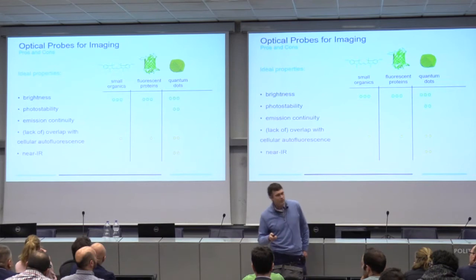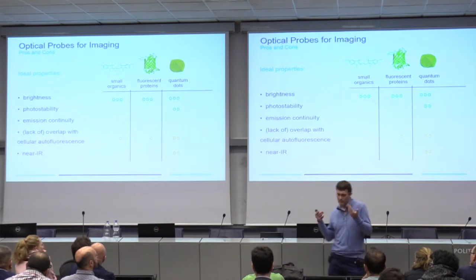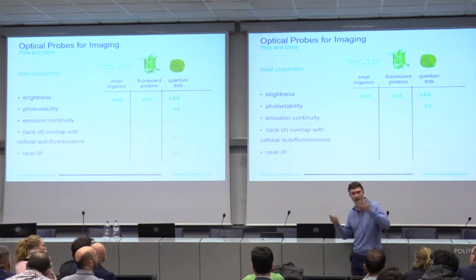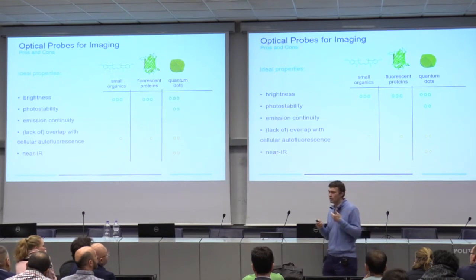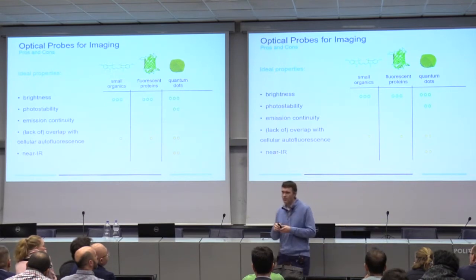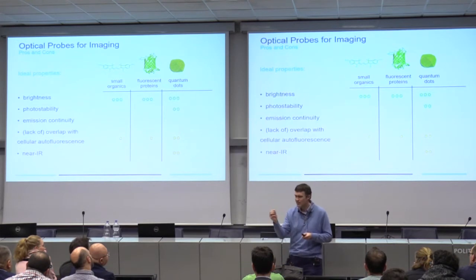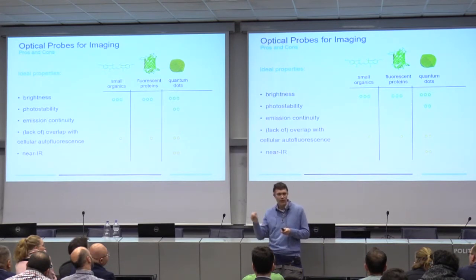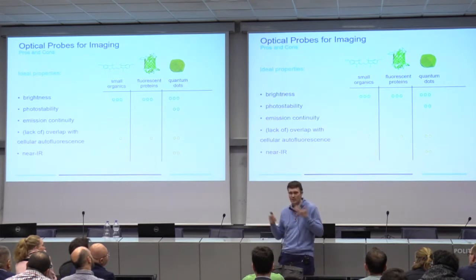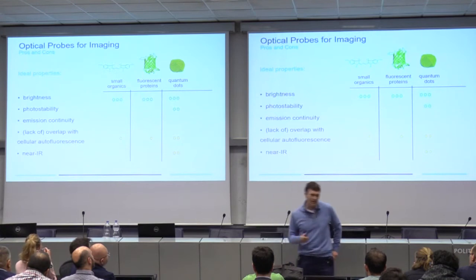Another issue is that all of these particles do this so-called blinking. So they turn on and off intermittently, randomly. And that's not always a problem, but it's a problem, let's say, if you wanted to tag a protein in a cell and track it, watch it move around. If your probe then turns off for a certain amount of time, it's impossible to track, right? And it turns out that all of these particles have this blinking problem.